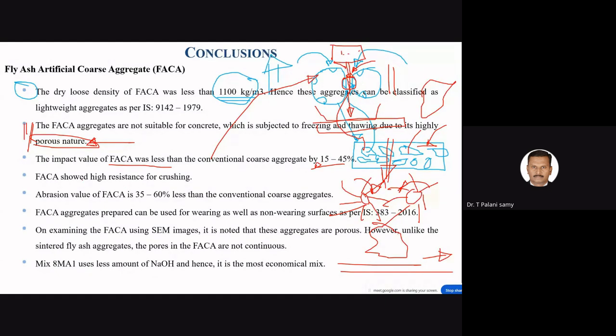Then FACA shows high resistance to crushing. The abrasion value of FACA is 35 to 60% less than the conventional coarse aggregate. We try to improve these kinds of things. The FACA aggregates prepared can be used for wearing as well as non-wearing surfaces as per IS 383-2016. On examining the FACA using SEM images, it is noted that these aggregates are porous. However, unlike the sintered fly ash aggregates, the porosity in FACA is not continuous, which means we have some advantages also.